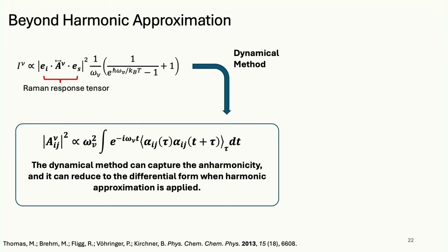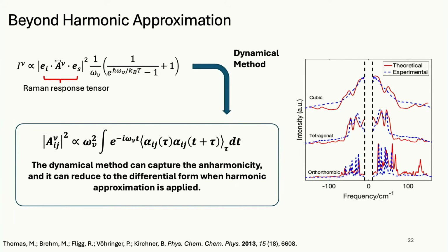Okay, and when we do that, look at what we get. Remember, we had this featureless blob. I would say the red that we get is pretty close to a featureless blob. When we go back to low temperature, we get modes. And then we get a weird double peak. And then we get this interesting featureless blob. So it actually can be captured in the theory. And so then we can set about saying, okay, now what's going on? Because we have a glimpse into what every atom is doing at every moment in time.